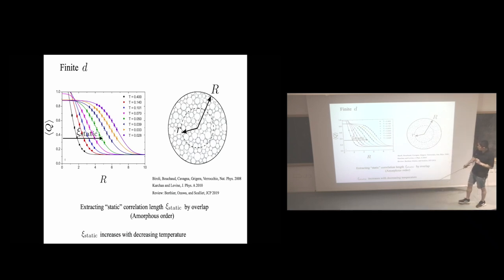Okay. And I want to mention that Jorge Kurchan and Dov Levine have another perspective in terms of amorphous order. Okay. And what we can find in finite dimensional simulation is a growing static correlation length with decreasing temperature, as expected from a random first order transition scenario. Okay, so to conclude, in terms of the thermodynamic aspect, the mode coupling temperature is not a phase transition anymore, it's just a crossover, but still useful.